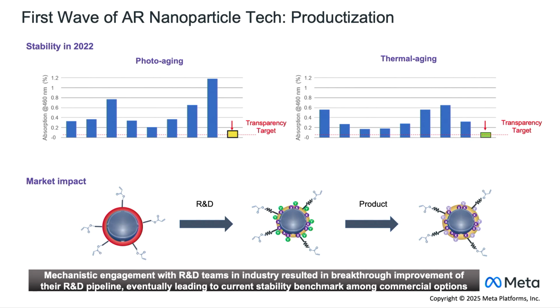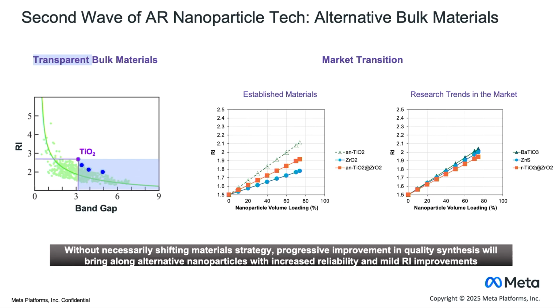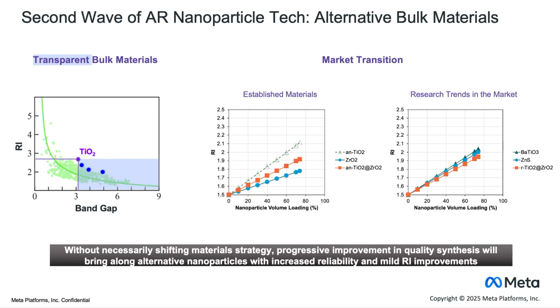Now, the second wave of AR nanoparticle tech is something that's currently unfolding. So we have many different R&D efforts across the industry to try to make more stable and high refractive index materials. The approach that the field as a whole is taking is not very different from what we've done already, okay? So we're also looking at transparent bulk materials, and what we're doing here, instead of focusing on titania, is just choosing materials that maybe have a lower refractive index, but because they're not photoreactive, they're more stable, then we don't need to build so many layers and passivation species around them, so the refractive index turns out to be maybe slightly higher, and what we're trying to buy here is a little bit of improvement on reliability. So I think we will be seeing this in the market from many different types of sources soon.